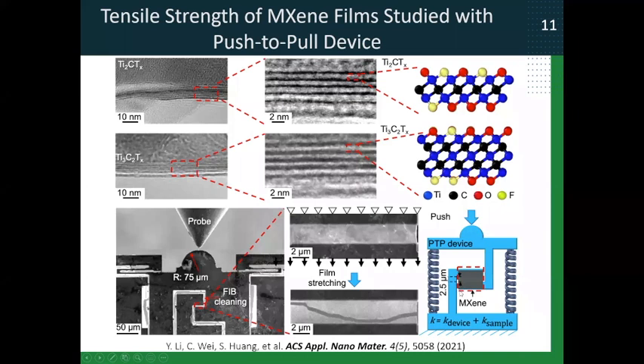And we deposited MXene films over this gap, again, with a precisely controlled number of MXene monolayers, as you can see here, 1, 2, 3, 4, 5 layers, right? So we know exactly how many layers we have in this MXene film. And then we start to stretch it with, again, a known force, and we observe how it behaves. Eventually, of course, it breaks when we stretch it above a certain limit. But before that failure happens, we can record data on force and displacement and produce, again, stress-strain curves. But now these curves are for multi-layer MXene films with a precisely controlled number of monolayers.